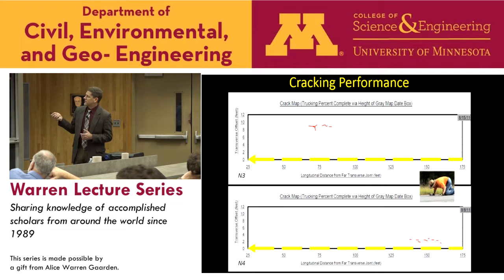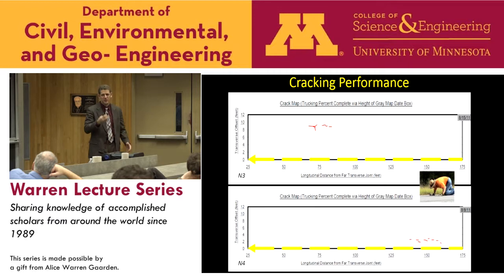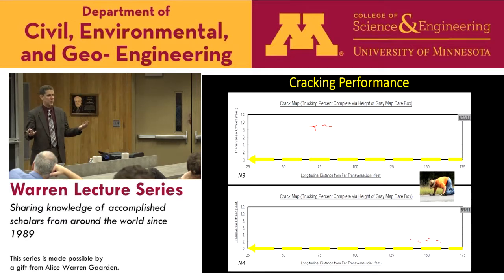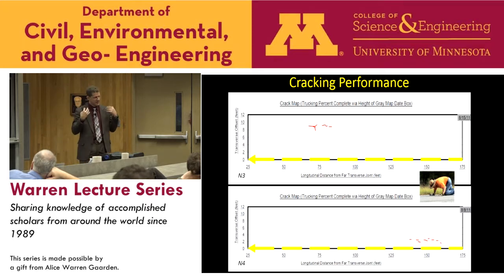So what we're showing is a map of the test section. Traffic's moving from right to left, and we saw some cracking here in section N3 and some cracking here in N4. Naturally, when we decided to take them out of service, we said we've got to cut them open and see. If it's bottom up, it's kind of game over. We can't call it perpetual. If it's top down, then that's behaving as a perpetual pavement should. Eventually you may see some top down cracks as the pavement ages and becomes stiffer and so on.